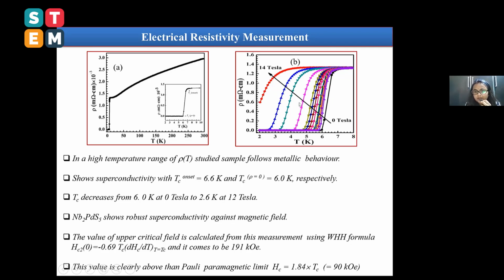And here you can see that this is the temperature dependent electrical resistivity at different magnetic fields. With increase of magnetic field from 0 to 12 Tesla, TC reduces from 6 to 2.6 Kelvin. That is, it shows robust superconductivity against magnetic field. From this measurement, we found that the value of upper critical field is 191 kilo oersted using the WHH formula, minus 0.69 TC dHc2/dT. This value is clearly above the Pauli paramagnetic limit, which is defined as 1.84 TC, in this case 90 kilo oersted.